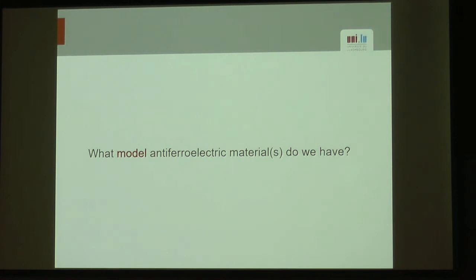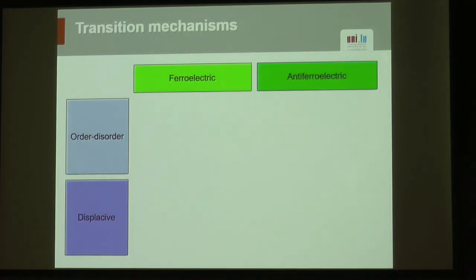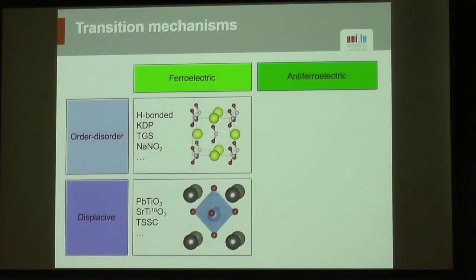So obviously, in terms of models, I don't need only one. I need at least two, and this is because if I make a comparison with ferroelectrics, we typically distinguish between order-disorder and displacive transition in ferroelectrics. And in ferroelectrics, without going into details, there's a lot of order-disorder transitions. This is just an example for this, sodium nitrite, for example. And for displacive transition, the typical one is probably a titanate. And this is also well known for quite some time.